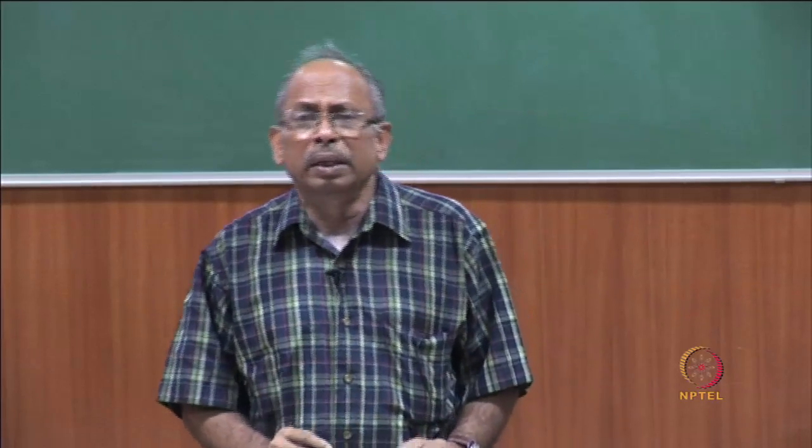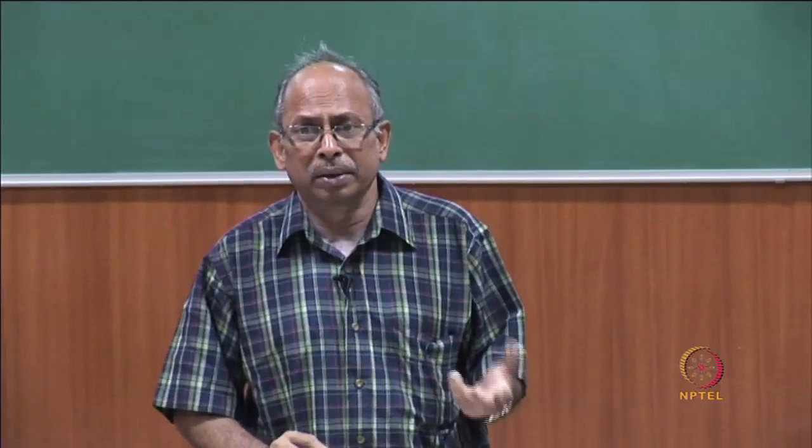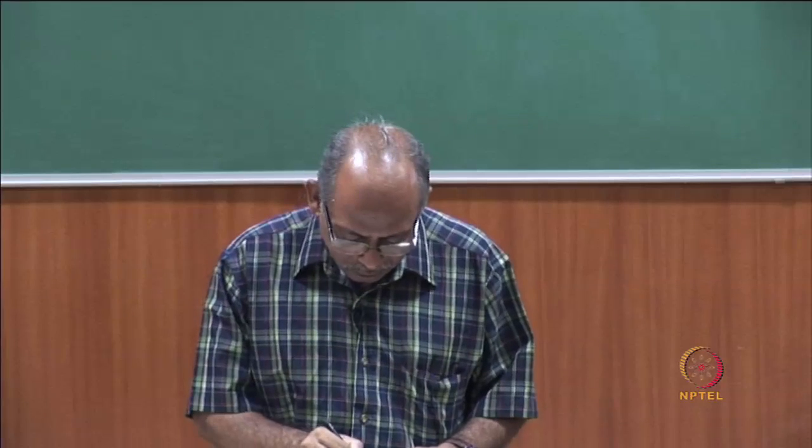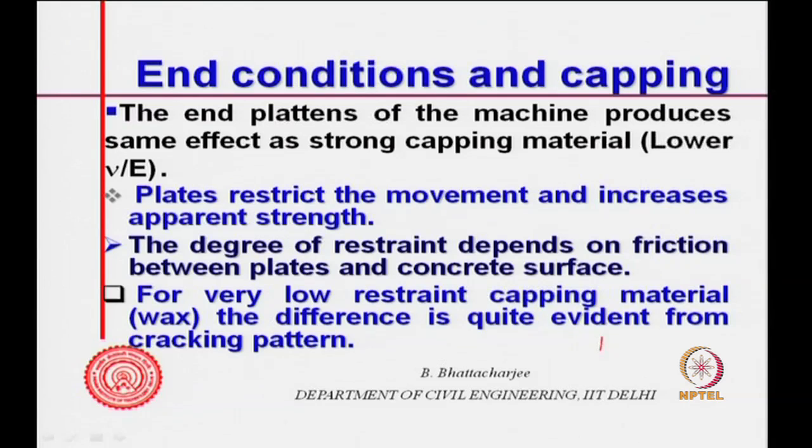There is something called brush platens, made of closely placed steel brush. So, you use a brush below the plate. The brush can expand easily, although it will not fail. So, that is the platen effect basically.